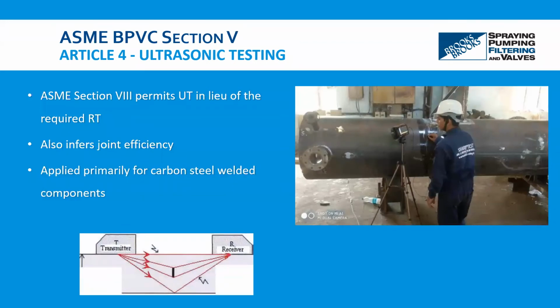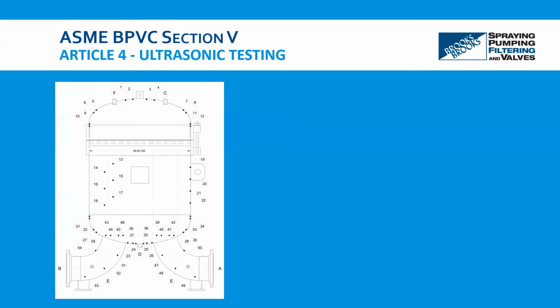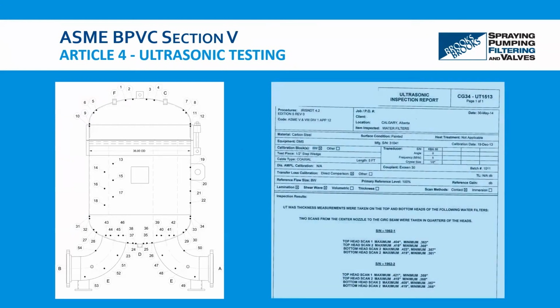We can see the setup here where it is employed. You have a transmitter and then a receiver. This configuration is typically employed, and now we're going to look into how that might be implemented in a report. We'll look at an example of an ultrasonic test used to measure thickness. Prior to the inspector conducting the test, the designer would have to identify the areas of interest. You can see here where they're labeled. Upon completion of the ultrasonic test, you would receive a similar report to the right, which indicates the thicknesses garnered from the test. This confirms that the measured thickness in fact meets the minimum thickness requirements in the design calculations, similar to what we've done before.